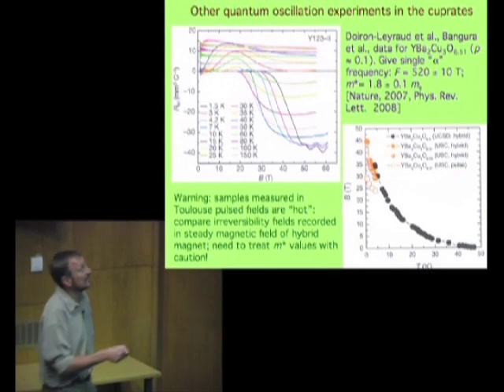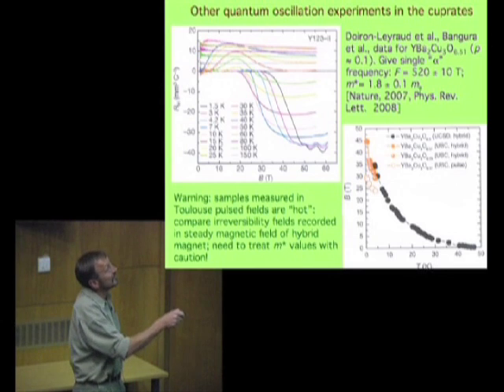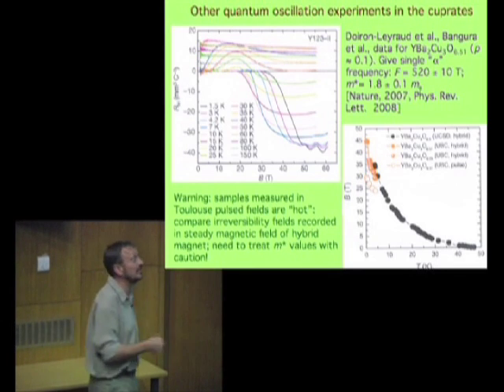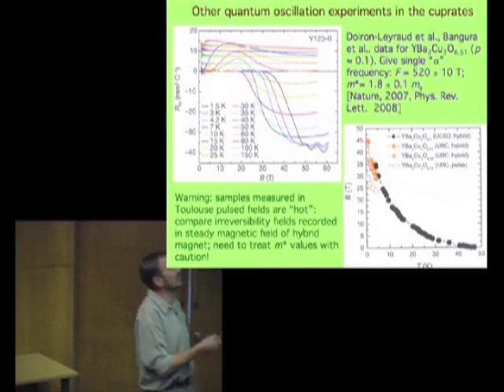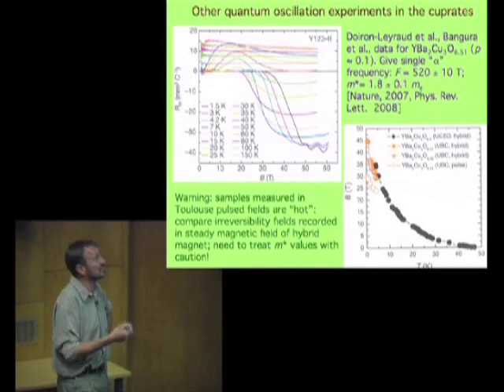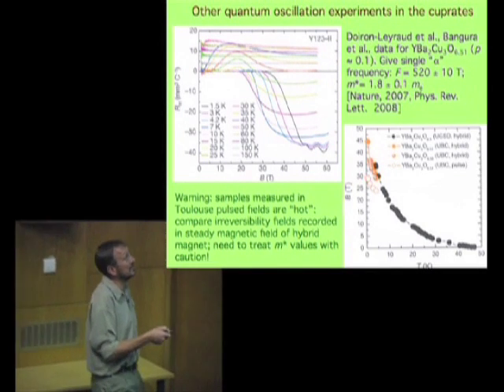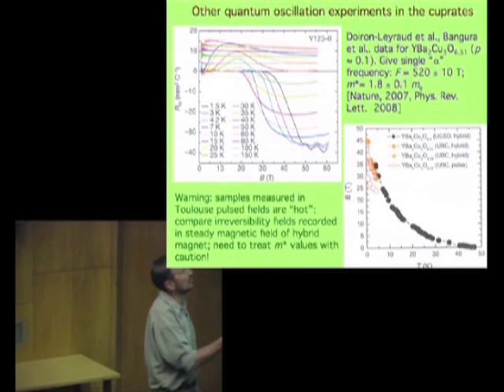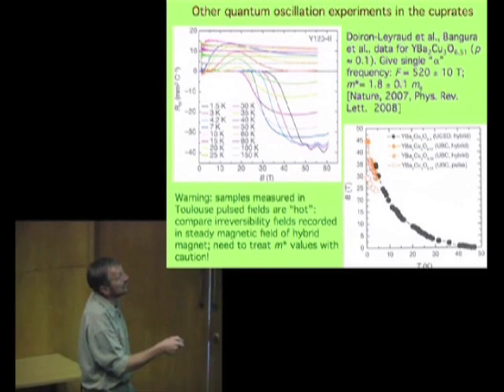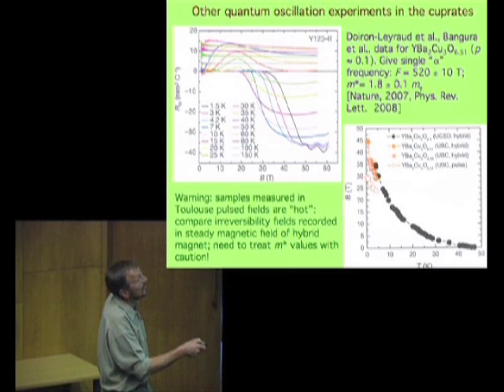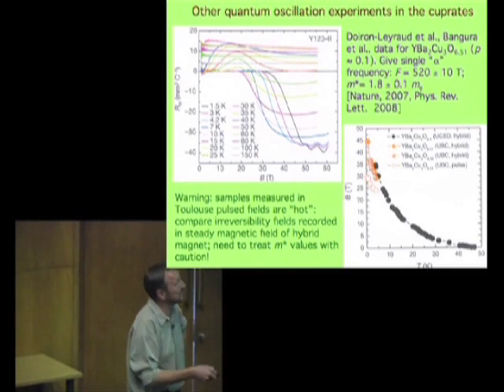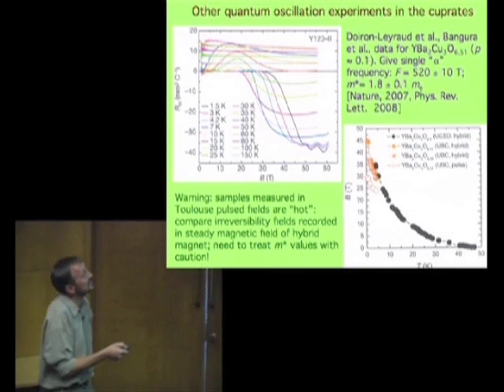And the reason is that there's a lot of sample heating going on. This region again has this lossy kinetics, and because of the experimental system that they use, which has the sample in low pressure helium gas, the cooling is not very efficient. So you've got a high temperature here, and this has skewed the effective mass. As we'll see later, you actually have a heavier effective mass.